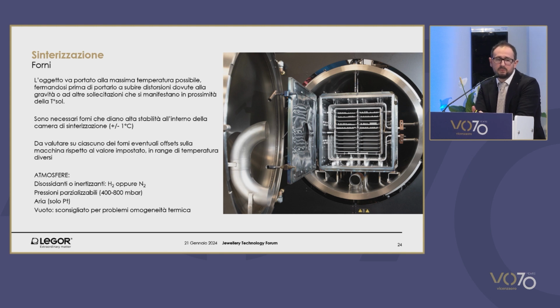After curing and debinding, the true sintering process starts. That envisages specific atmosphere depending on the type of alloy, depending on the type of material. Sintering ovens that are compatible for MIM, where the binder content is still pretty significant when the item is placed in the oven, envisages the use of reducing atmospheres with partial or total pressure, hydrogen, or the possibility of insufflating during some parts of the cycle inertizing gas like nitrogen.